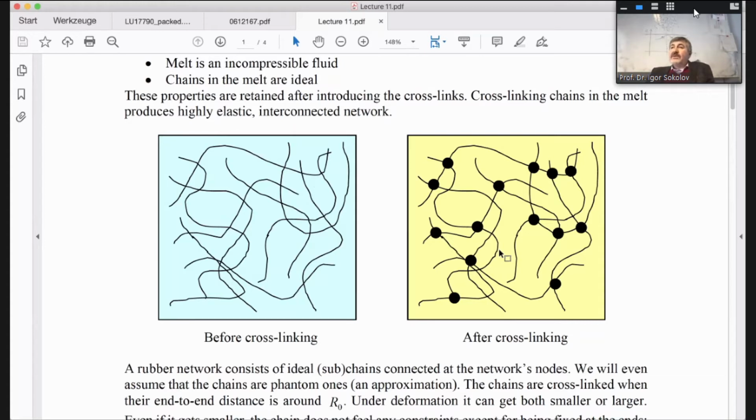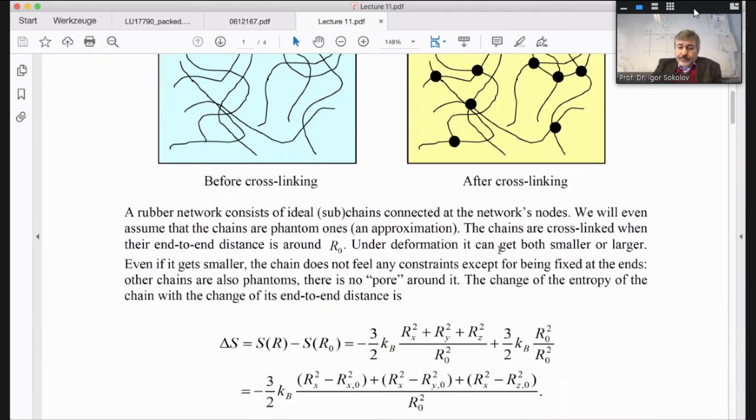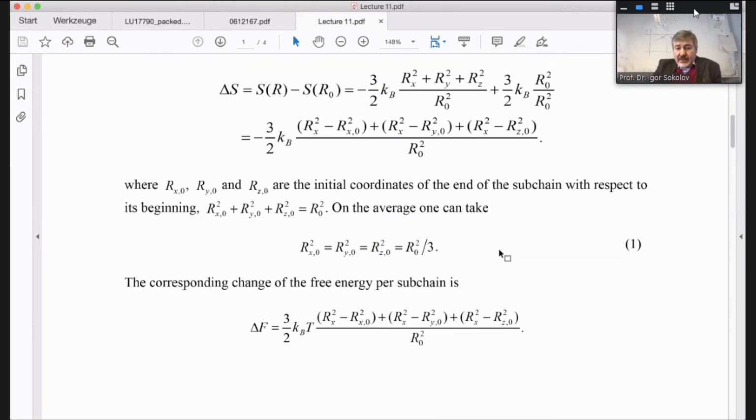Essentially, I have to disregard them only partly because there are also physical connections. The two loops which might pass through each other still give you a physical connection, which is the true cross-linking, because you cannot separate chains by whatever translation anymore. So essentially, if you want to build a full theory, it's extremely complicated. And I have never gone through the full theory, although I know people who did it. But if you want to stay simple, you can stay simple.